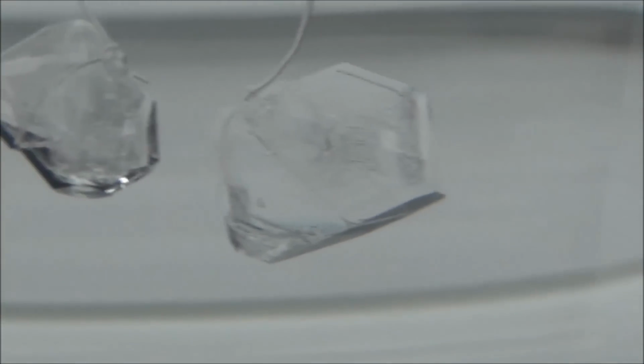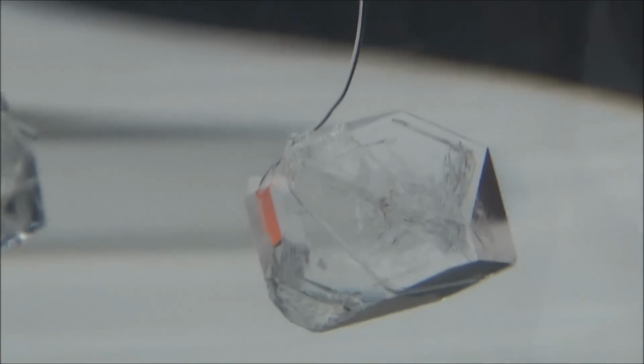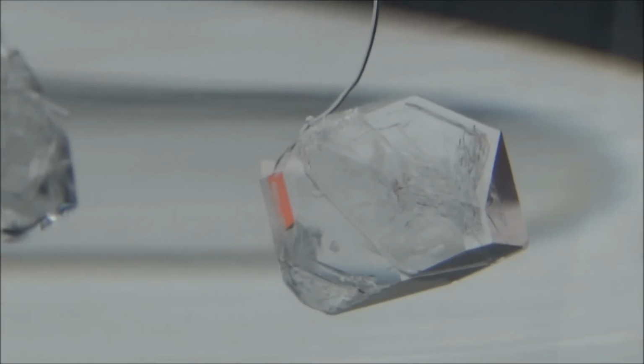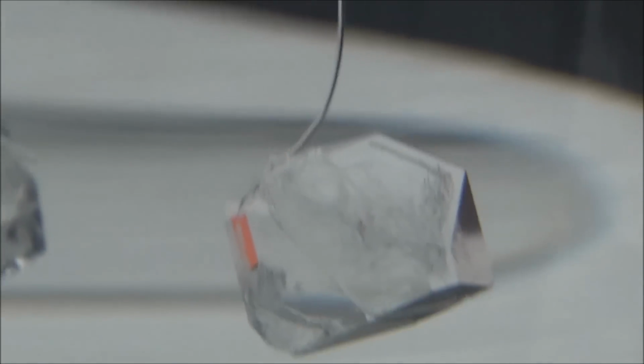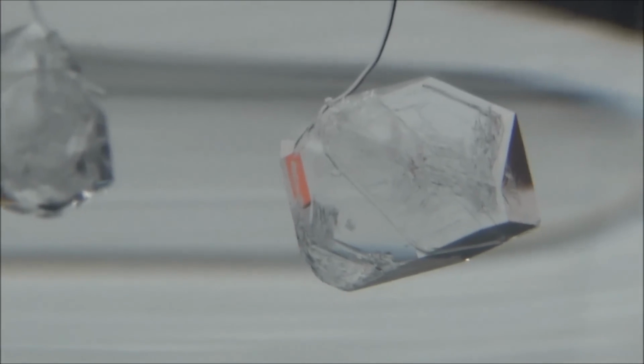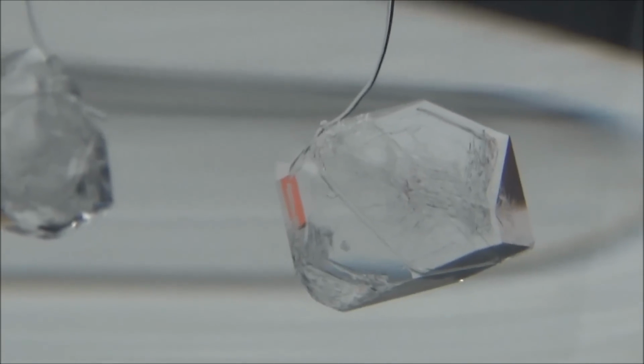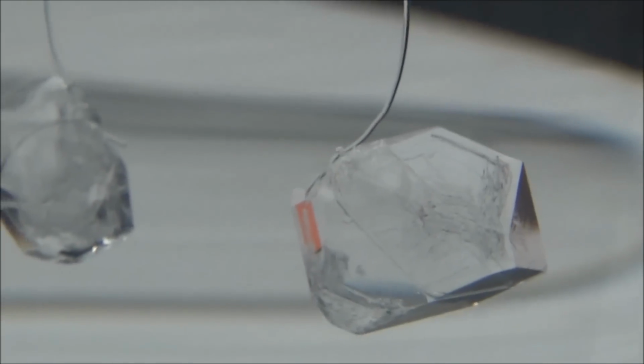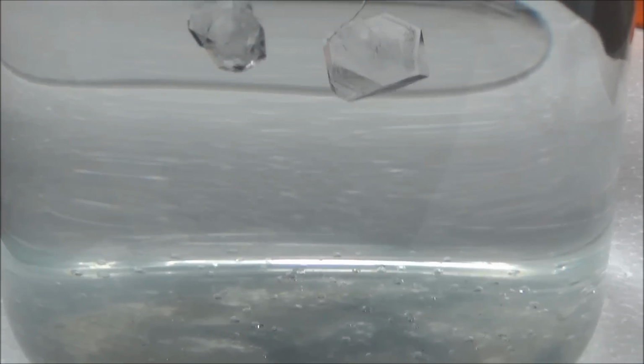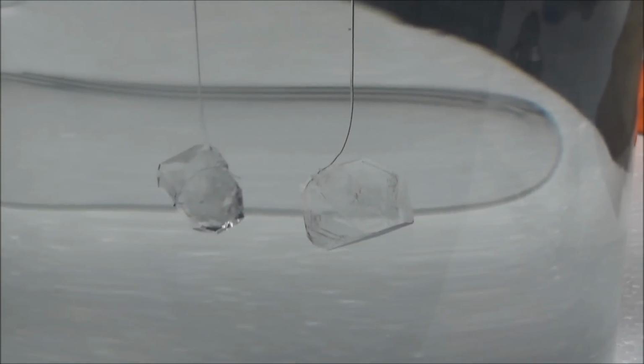Now, this is the big crystal, and you can see it looks pretty nice. It's a single crystal. There are a few little occlusions inside, and there was a little crystallite sitting on the top that I knocked off a few minutes ago. But there's a couple things I just want to point out in the beaker. One is, if we go down to the bottom, do you see all those little crystals growing in the bottom? That's a sign that our solution is a bit too saturated, that not all of the material was able to just grow straight onto the crystal.